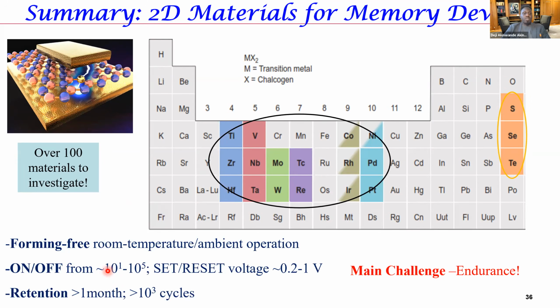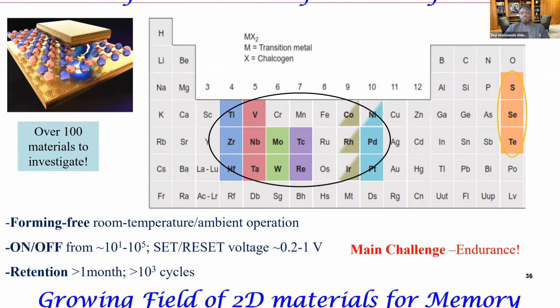The properties of these materials are that you can get very good on-off ratios, orders of magnitude, even though they're less than a nanometer insulating barrier. Voltages are very, very low, energies are low, it can endure for a long time, can be cycled, and we just need to improve the reliability. This is what the industry, every time they call me on the phone, keeps asking: when is it mature enough for commercialization? And unfortunately, it's not, because we need to make sure it's much more reliable. And this is kind of the most difficult research to do in an academic lab. Its reliability is more of an industrial level effort.